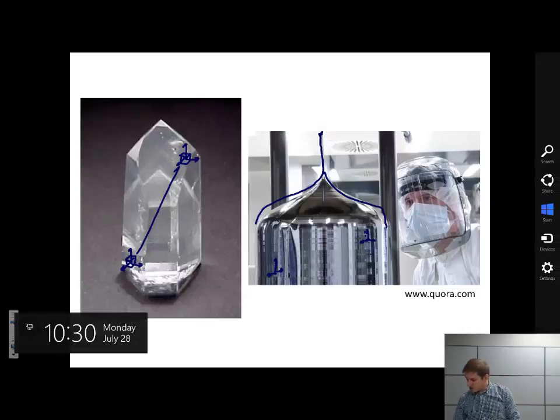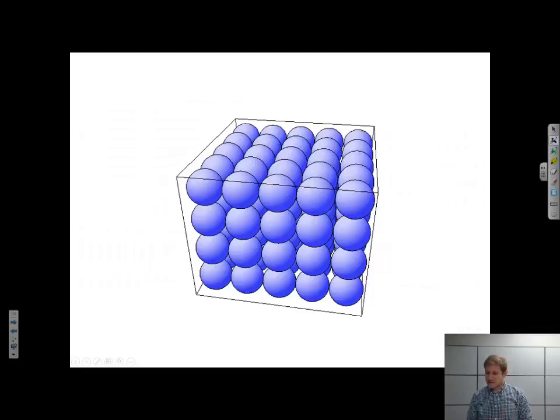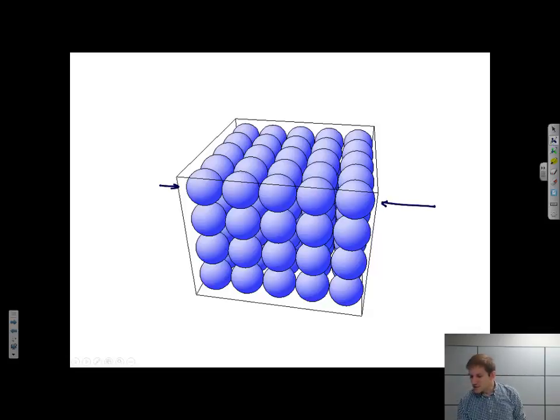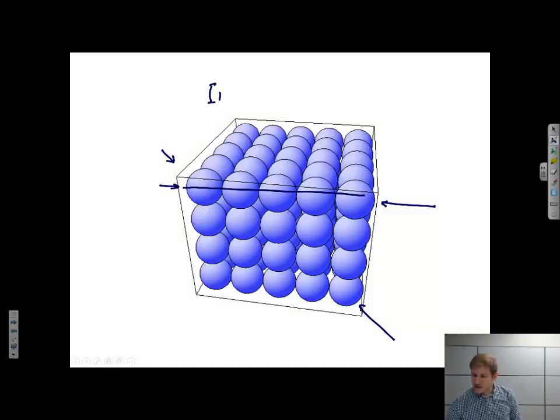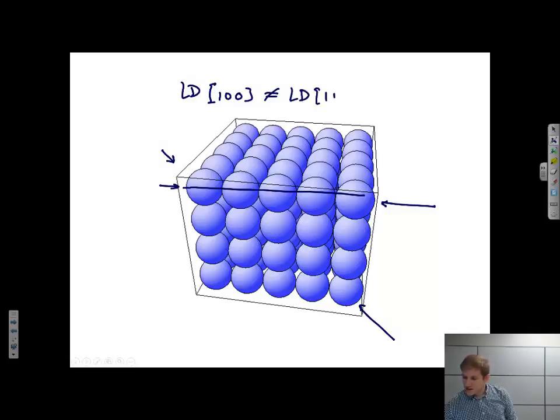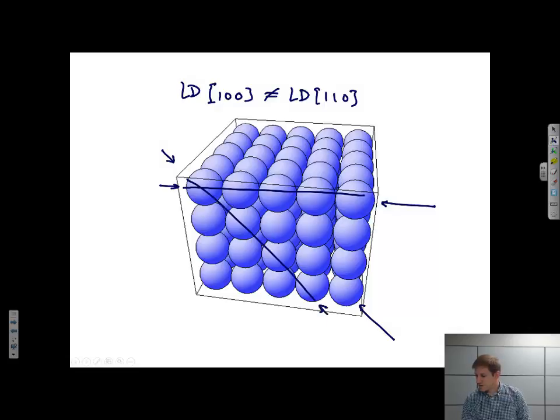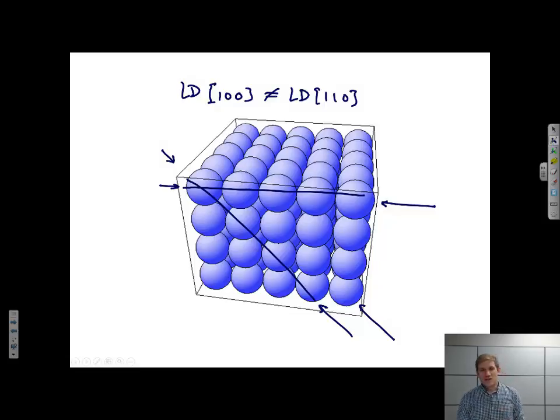Let's talk about the physical properties of a single crystal substance — maybe electrical transport, maybe the elastic modulus of a material. The important thing is to think about how those atoms are oriented in one direction relative to another. We talked about linear density before. Looking at a simple cubic crystal, the linear density in the 100 direction is not the same as the linear density in the 110 direction. The atoms are spaced a bit further apart, and the electronic orbitals aren't overlapping as much as they are in the 100 direction. So it makes sense that the physical properties in these two directions are different.